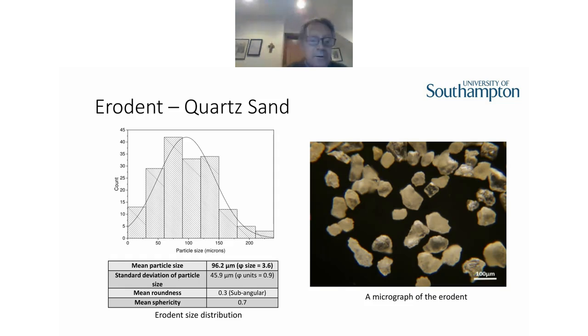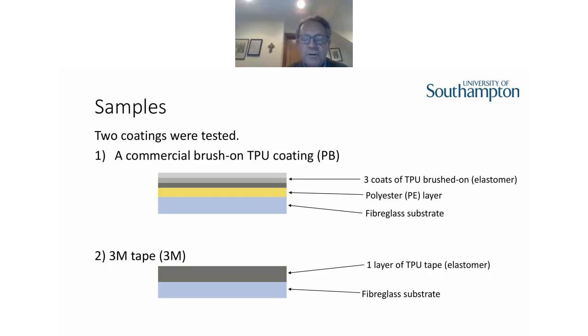The erodent that we chose was semi-rounded quartz sand, with quite a wide particle distribution, although the average is just under 100 microns. The distribution here is quite broad, so there were quite a number of small particles, which I'll come on to later, and equally some larger than 100 in the mix. So that was the type. They are quite angular, and there are some rounded, so you're likely to get a slight mixture of erosion mechanisms just because of the shape of the sand.